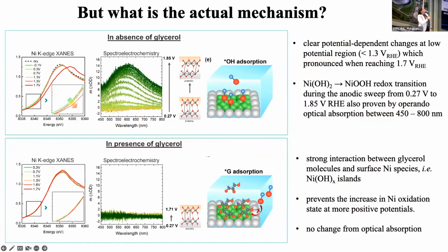And we combined this nicely with spectroelectrochemistry in collaboration with James Durrant in my department, and we really see the nickel hydroxide transition to this nickel oxyhydroxide, especially at higher potentials. But when we work in the presence of glycerol, we actually saw no change anymore. So that means the glycerol is really blocking the nickel surface from being oxidized. And so you don't have the bimetallic mechanism, you just have nickel changing the electronic structure. It's very nice to see the match between the XAS and spectroelectrochemistry, where you see no change in the oxidation state here, which is quite nice.